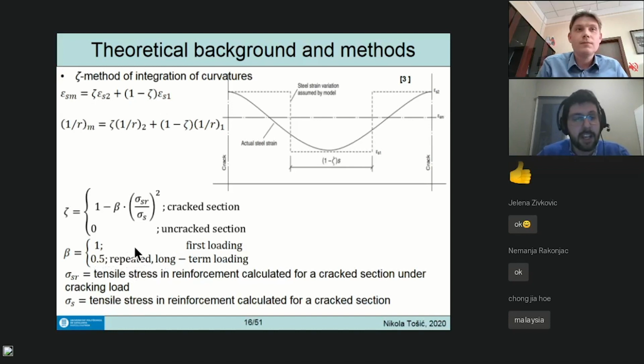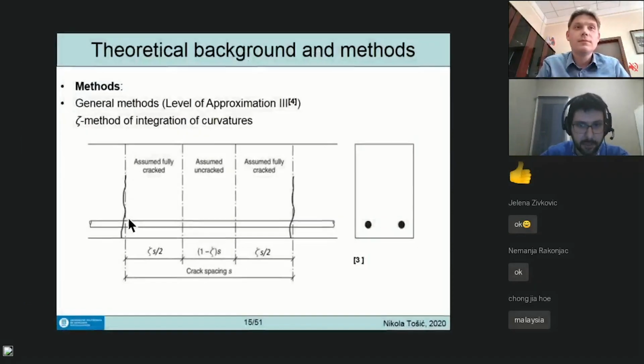What does this mean? So when beta is smaller, we get a higher Zeta coefficient, so we're closer to state 2. Basically, this 0.5, you will see later when we move into moments, represents the gradual reduction of the cracking moment over time due to shrinkage, and the fact that over time we are more and more approaching state 2, as was shown on the previous image.